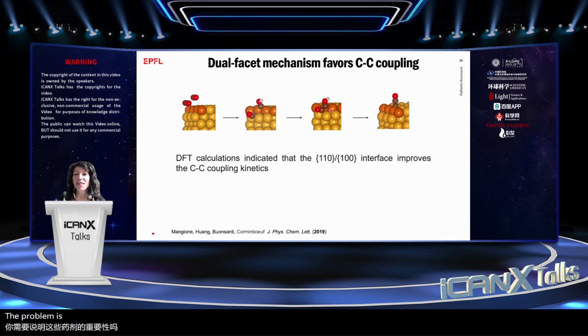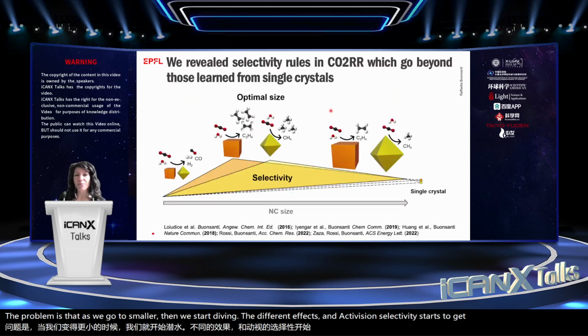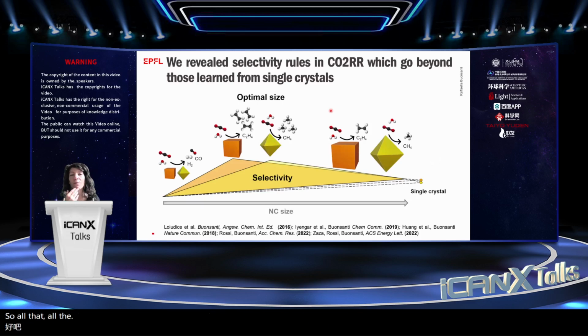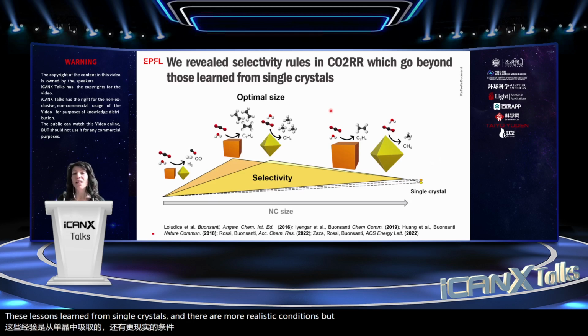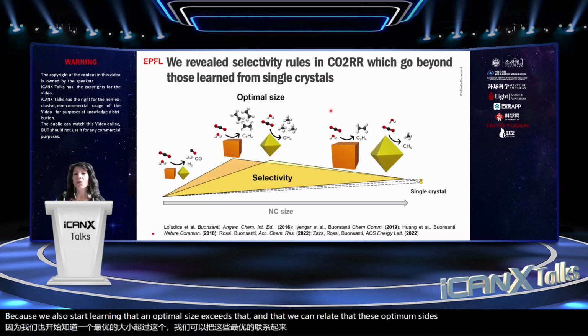The problem is that as we go too small, then we start having different defects and ethylene selectivity starts to get suppressed. So overall, what we learn from these shape-controlled nanocrystals is that, yes, we can translate these lessons learned from single crystals under more realistic conditions, but we can also go a step beyond, because we also start learning that an optimal size exists and that we can relate this optimal size to the presence of edge sites on the particles.